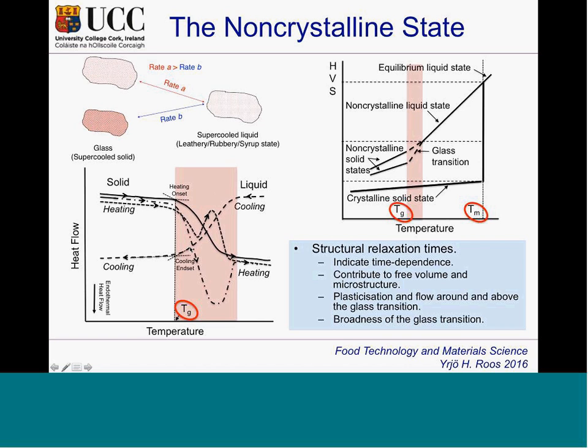But that goes to the temperature dependence of the glass transition itself. It goes to its non-equilibrium nature, because you never ever can do one single glass exactly the same again. That is because the molecules freeze and find positions that are dependent on the cooling or heating rate. And we could say that if we cool a material with rate A or rate B, we would have a different volume. If it is very slow, certainly we have a lot of volume disappearing from the material. If it's very rapid, we have extra free volume. And that is also relating to the enthalpy content of a material.